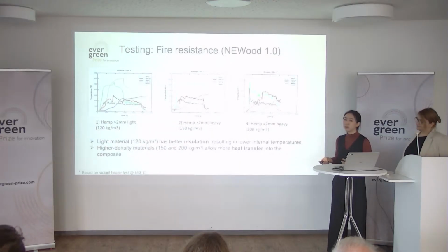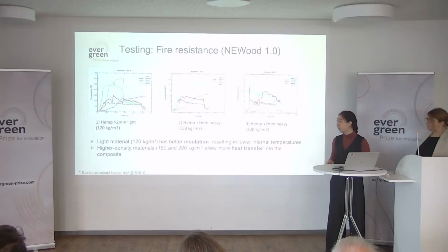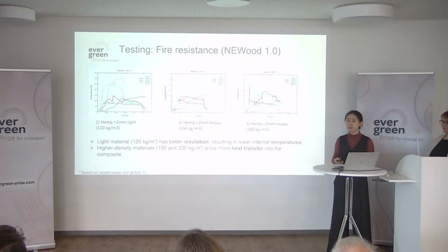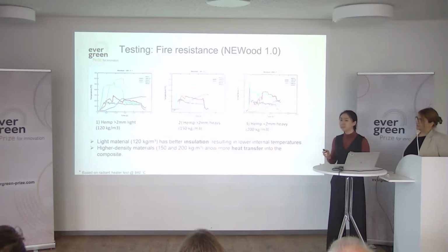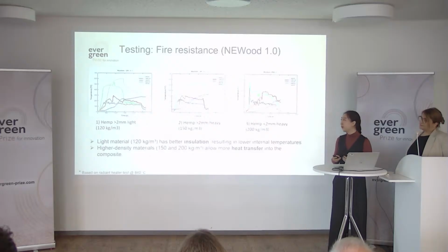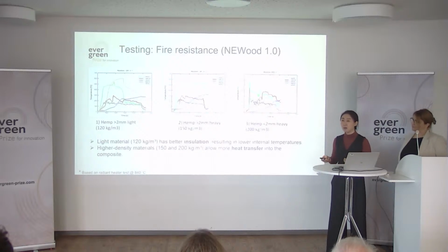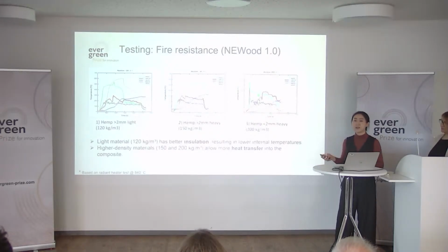We have also conducted some preliminary fire testing, and what we found was that light material, the very low density material, actually is a very good insulator. This is because there are many air pockets in the material, and that actually helps to insulate the heat from the inside and from the other side of the material when we are doing the testing. We also found that it does not emit any harmful or toxic gases into the environment because it's completely natural. So you will not have that strange mixture of nitrous oxide and the other harmful gases that was mentioned by Nas just now.